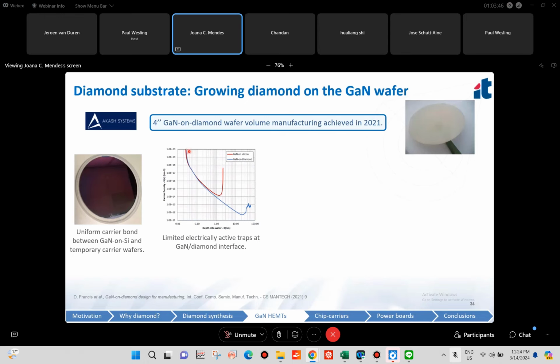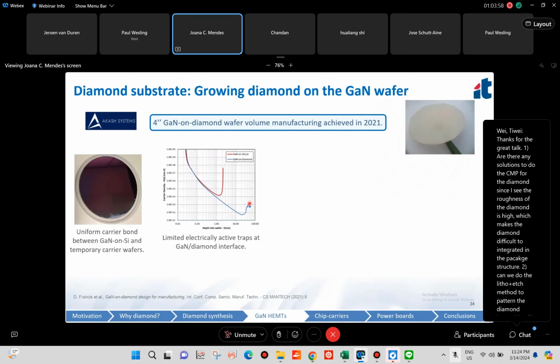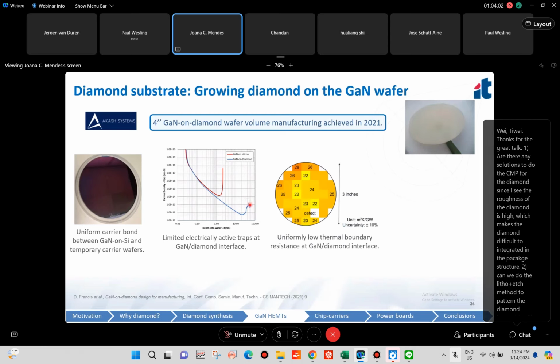Actually, as you move away from the channel, you see that the carrier density decreases. And here on silicon, you see the effect of traps, but in diamond, we only see the effect of traps after 10 nanometers into the channel. So this behaves even better than GaN on silicon.